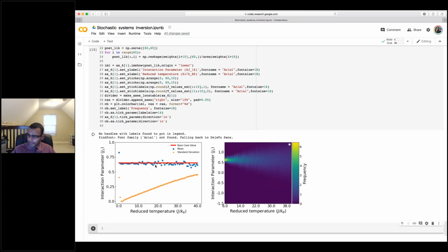Anyway, this is a really striking plot in many ways because it shows you a bunch of things that are not quite intuitive, right? You might assume that we should be right at the phase transition or really close to the phase transition to get really accurate results. But apparently this method shows you don't have to be. You can be quite far away from the phase transition and still get meaningful reconstructions. I'll leave it to you.